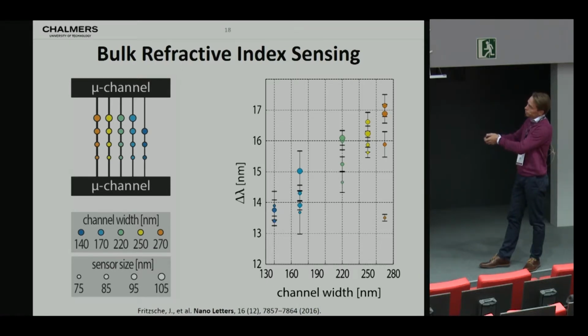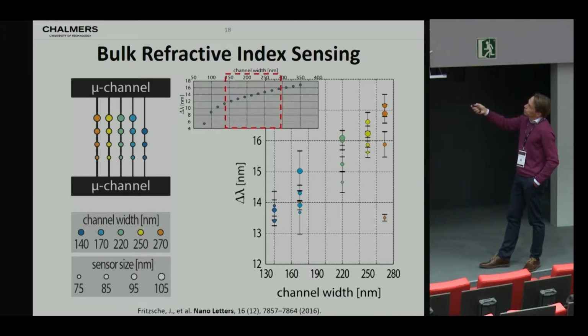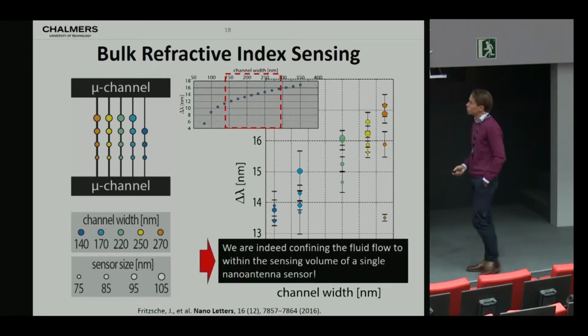So then we designed the chip to enable experimentally assessing this problem, where we have 6 channels with 5 different widths, decorated with 4 nanoparticles of 4 different sizes. Here I then plot the peak shift we measure for these particles as we exchange the liquid in the channel from water to ethylene glycol for the different channel widths, and you see that there is some sort of linear dependence, which is in very good agreement with our simulations for the range of channel widths that we have considered in the experiment. So what do we learn from this?